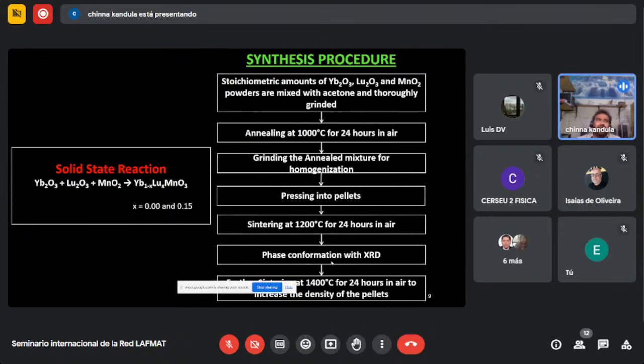When I'm making the pellets, I apply around 7/10 of the pressure in order to get a good pellet. Again, it is sintered at 1200 degrees centigrade for 24 hours. Generally, in solid state, we need high temperature in order to eliminate the impurity peaks and get proper phase mixing, so we have to go up to 1200. Based on the previous literature, I optimized some of the conditions where I got a single phase. So these are the optimized conditions I got.